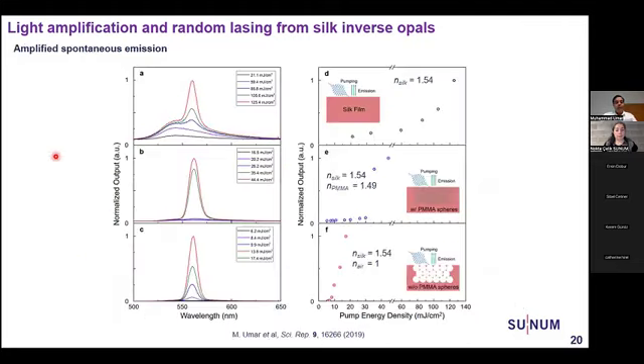So we found that, as you see, in the bulk silk film we have amplified spontaneous emission, but the threshold is very high. But whenever we are adding PMMA spheres, the threshold is getting lower because there is a refractive index mismatch between the polymer and the spheres.